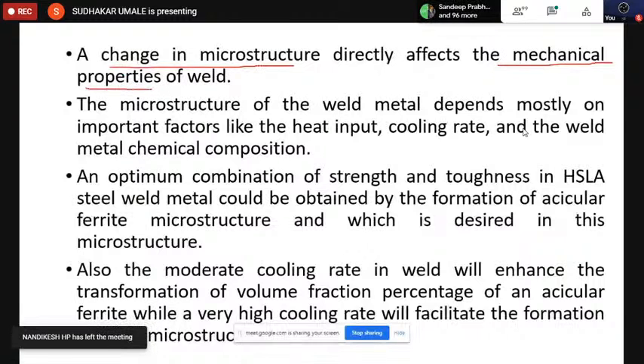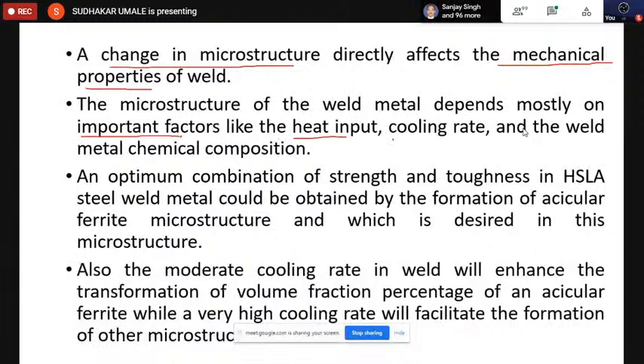This is my study. And this microstructure of the weld metal depends mostly on the important factors like heat input, cooling rates, and weld metal chemical compositions. During that period, I have concentrated on heat input, cooling rate, and chemical composition of this. And optimal combination of strength and toughness of this weld metal could be obtained by the formation of acicular ferrite.